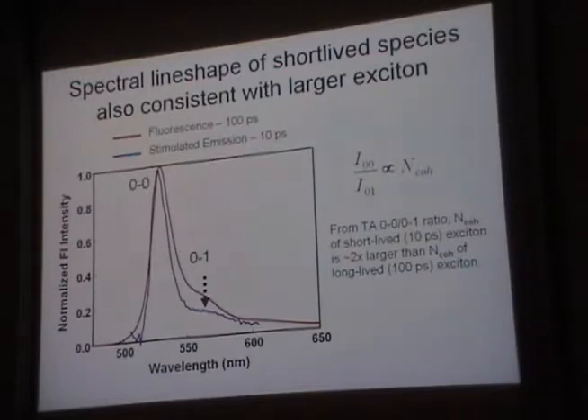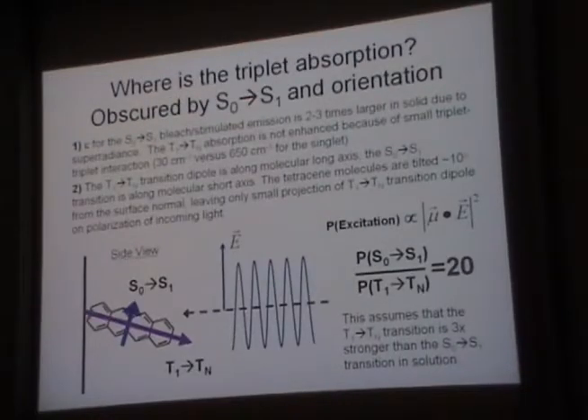So what we think actually is that the fluorescence that you mostly detect from Tetracene is probably due to what's called a linear slip dislocation defect, and we have better evidence for that in anthracene, which we published. And that this guy is some other, it may be a defect or it's something else. It's a new short-lived species that decays in a 10 picosecond time scale. So as you go farther in time, you see different states. That's the case. So that's why the singlet is so big.